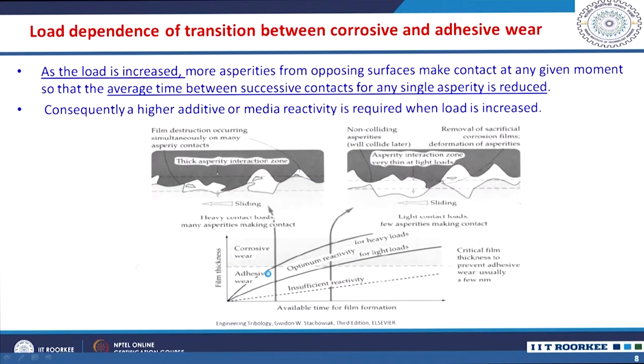As the load is increased, you will have a transition between corrosive and adhesive wear. Let us see here light loading conditions and high loading conditions, that is, light contact loads and heavy contact loads. As the load is increased, you see the film thickness and the available time for film formation. So, you will have adhesive wear and then corrosive wear. As the load is increased, you will have more asperities from the opposing surface that come in contact at a given moment.